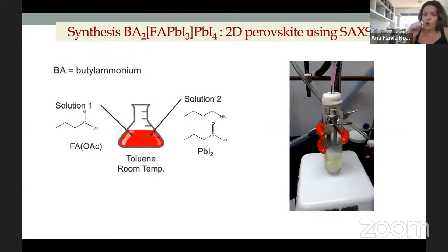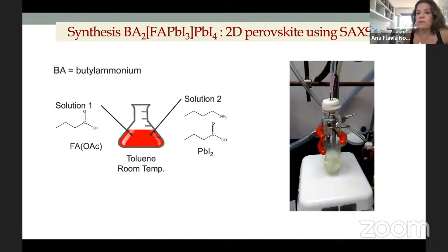Starting with probing the formation in solution. In this case, this was a 2D perovskite. As you can see here, this is the composition. We use this butylammonium, which for us is a kind of large molecule that allows you to prepare 2D materials. This was done by my master's student at the time, Rafael. He came up with this synthesis at room temperature, which I'm going to show here. It's very easy to synthesize. It's just a mixture of the two precursors.